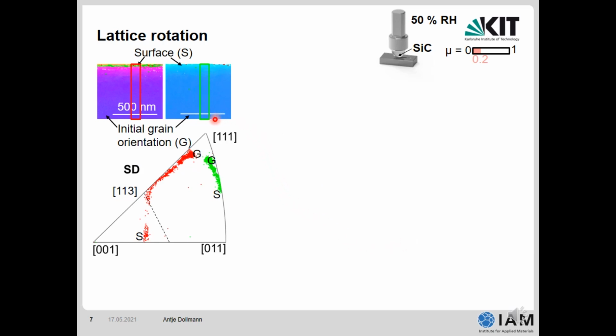We used the TKD measurement also to investigate the lattice rotation. Therefore, I have defined here these rectangles, and the orientations within these rectangles were plotted in inverse pole figures. Down here you can see the inverse pole figure in sliding direction. Furthermore, the initial grain orientation is marked, so here by a G, and also the surface orientation here and here. I usually compare these to what happens under uniaxial load because this is easier for me to imagine. And here in both cases we can see that the orientation rotates along a bisector, which is quite well known from uniaxial tests because here two slip systems are activated.